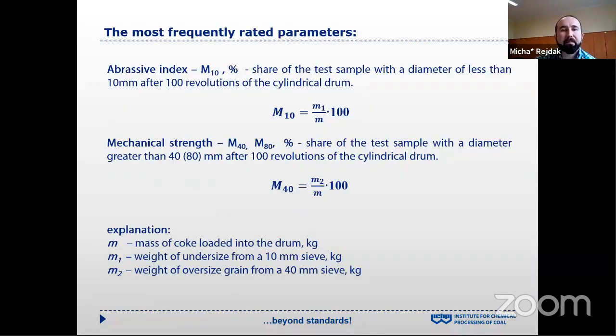And the most frequently rated parameter is the abrasive index M10, which reflects the share of the test sample with a diameter of less than 10 millimeters after drumming. And the mechanical strength can be M40 or M80. It reflects the share of the test sample with a diameter greater than 40 or 80 millimeters after revolution of the drum. In general, in aspect of blast furnace process, it is better to have a relatively low abrasive index and a relatively high mechanical strength.